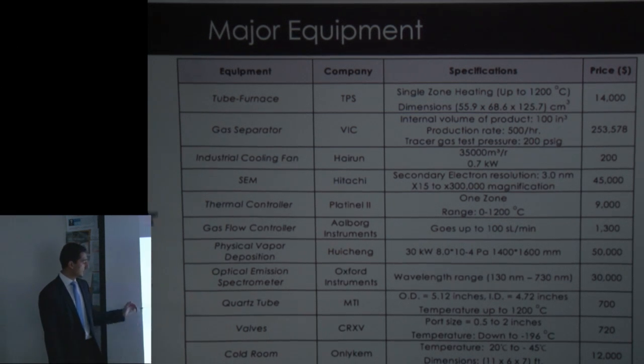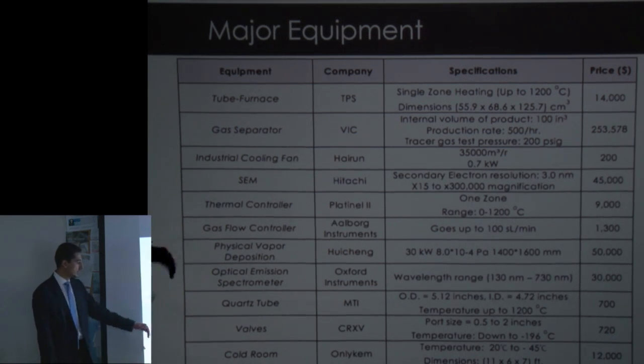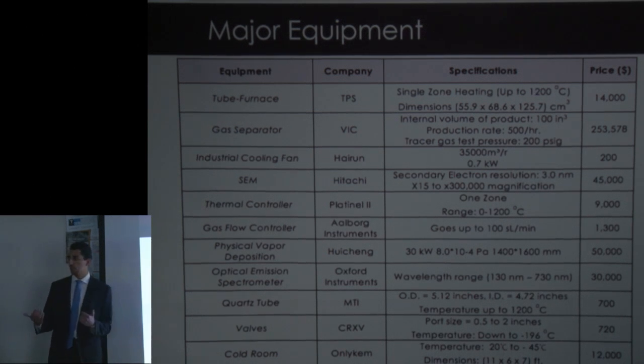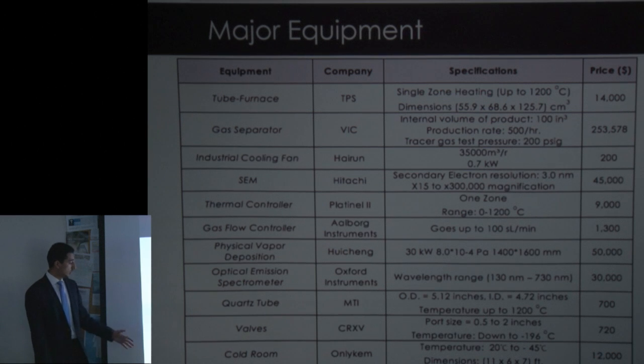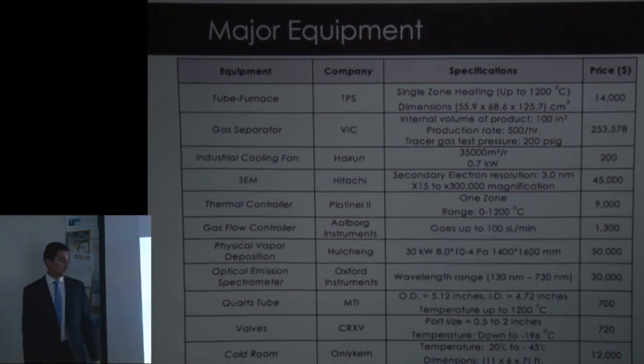For the SEM and optical emission spectrometer, they'll both be used for the characterization of our final product. We have used a couple of controllers as well for the gas flow and temperature. We're using a physical vapor deposition machine, which will do the electron beam evaporation on the copper substrate for coating. We're using a quartz tube, so it sustains the heat of our CVD reactor. And finally, we're using a cold room to store our gas cylinders of hydrogen and helium.